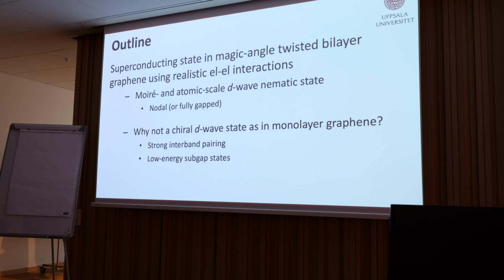It has both modulation on the Moiré scale, but also on the atomic scale, and they are both d-wave nematic states. And this state can be nodal, but depending on filling, it can also be fully gapped. So it's both, depending on the filling. And then if I have time, I want to contrast this to what would happen in monolayer graphene.